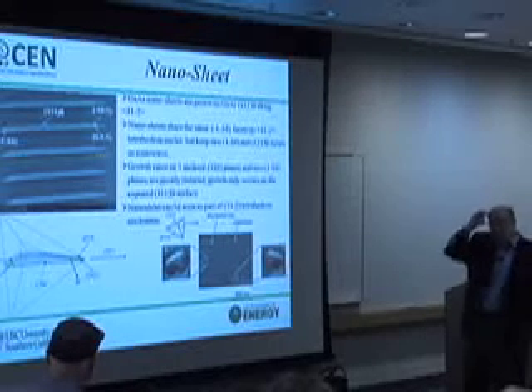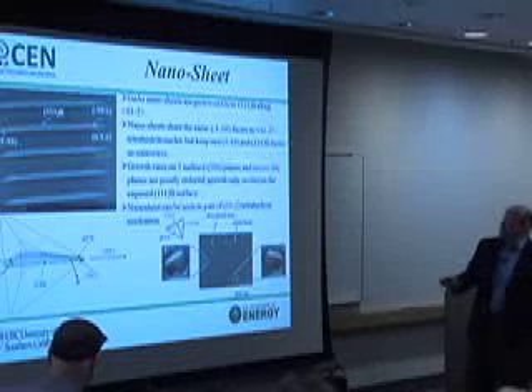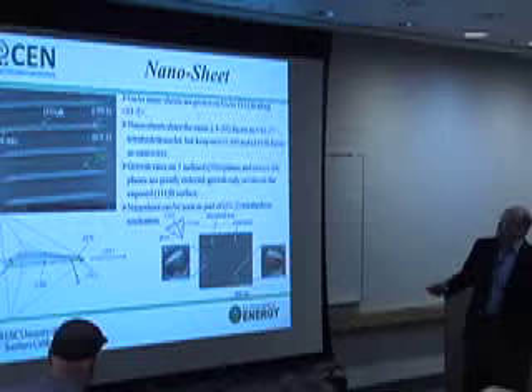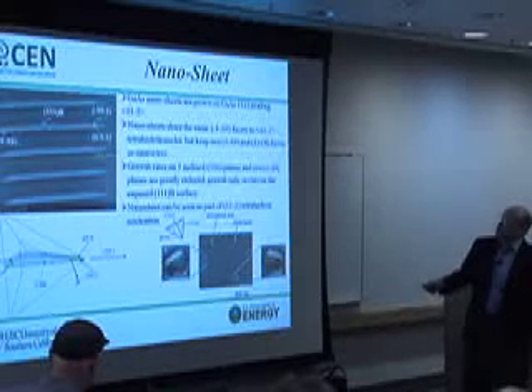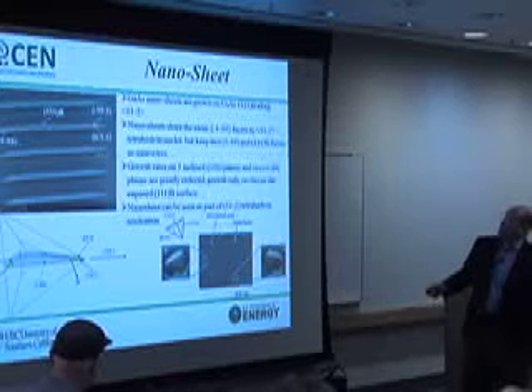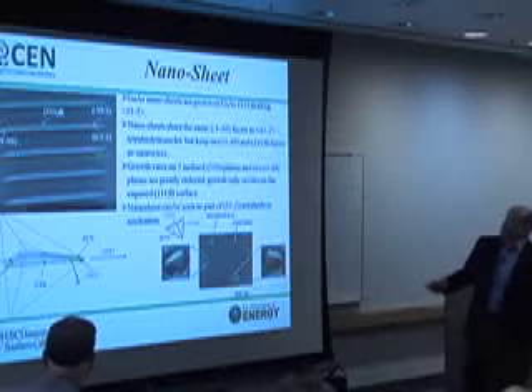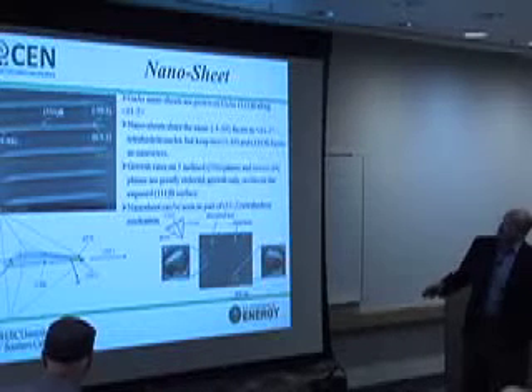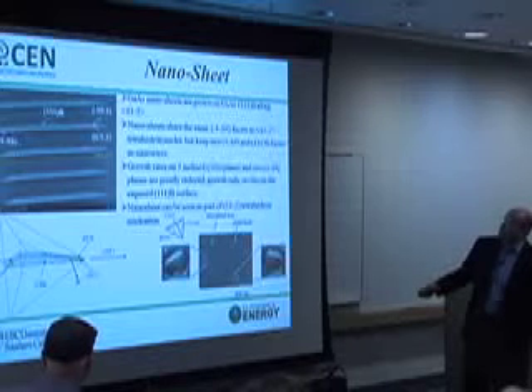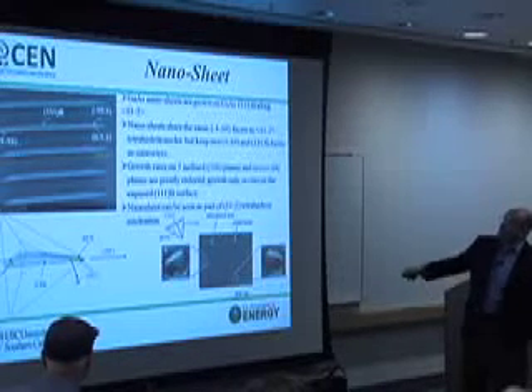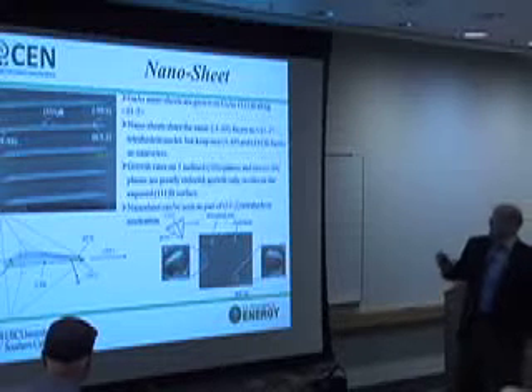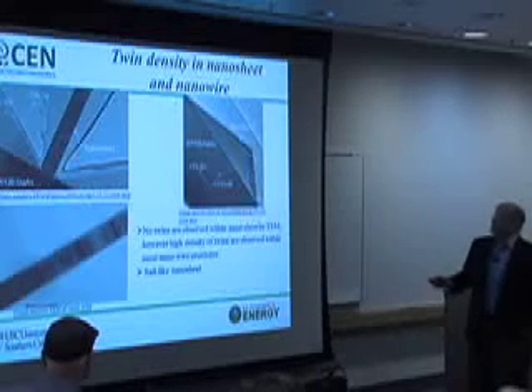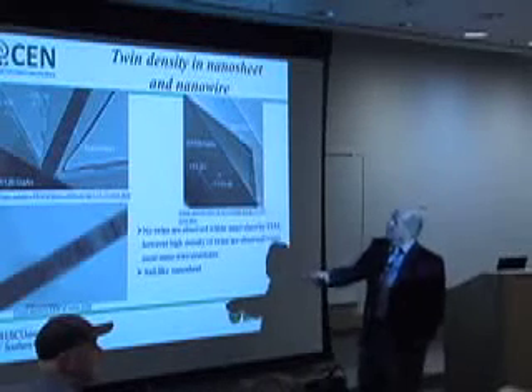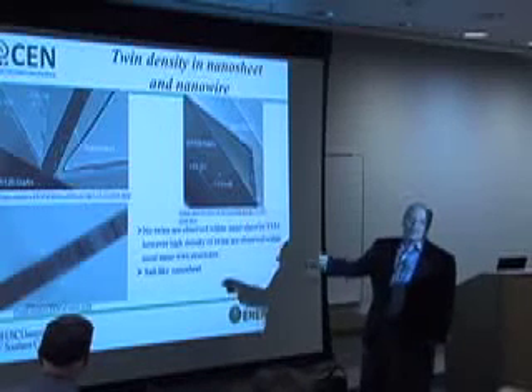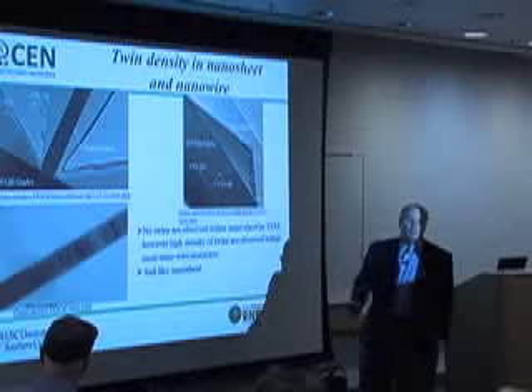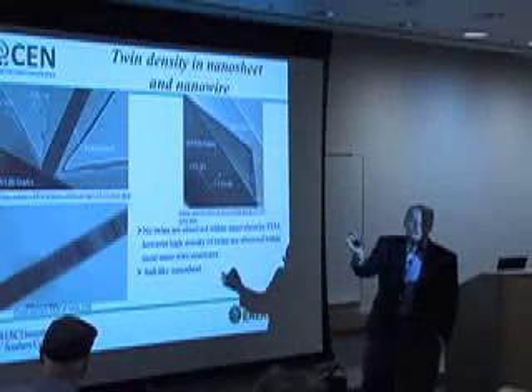So what we did is we changed the geometry a bit. We said, look, if these structures want to grow with this orientation along the 1, 1, minus 2 direction, why don't we form a thin stripe that's only 100 nanometers and see what happens. And sure enough, we grew sheets of material that, if you look at the details of the planes on them, look like they're a section cut out of a tetrahedron aligned along that direction. And I've got a whole story about this, and I want to rush through it because it's running late. But the bottom line is that there are no twins in that nanosheet at all. They grow perfectly with perfect 110 surfaces, no twins.